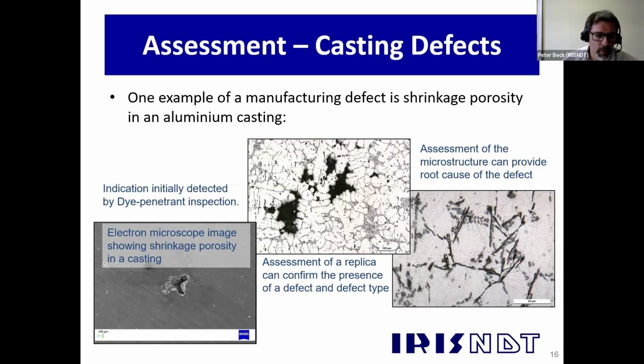So this is an electron image of the actual part. So you can see this pore, and you can actually just about make out the dendritic structure around where it's solidified. So it's basically a shrinkage porosity there.